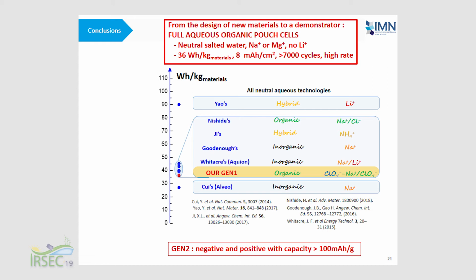We could go from the design of new kinds of materials to a demonstrator, so we are very happy about that. We get 36 watt-hour per kilogram of both materials in the cell. And of course, we need to compare this data to already published data. So here I put all the data published in neutral aqueous electrolyte, gathering all organic batteries, also inorganic electrode materials, and also hybrid system, organic on one side, inorganic on the other side. So you can see that our result scales compare quite well with most of the other results published.